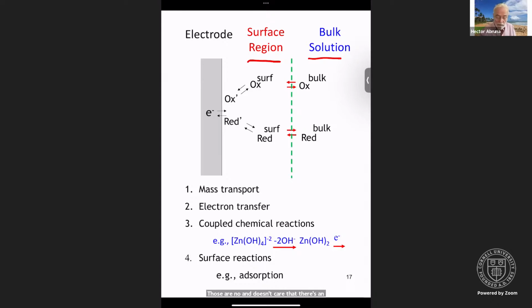There will be a region where the reactants will feel the presence of the electrode. It can be within the double layer region, where it's sensitive to the applied potential. It can also be the diffusion layer, which is the regime over which you can sustain a concentration gradient. So you feel the presence of the field, not because you're feeling the field directly, but because of the consequences of changing the effective concentration close to the electrode surface. As we had before, we go from bulk to surface, meaning that species feels the presence of the applied potential. From there, we go further and we call it Ox prime here, meaning that the species now feels a very intimate interaction with the electrode surface.